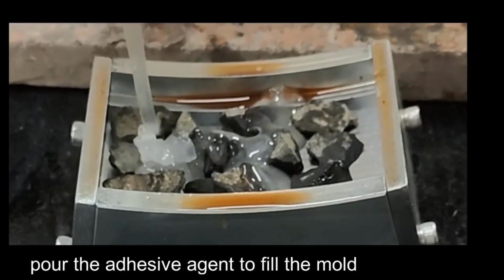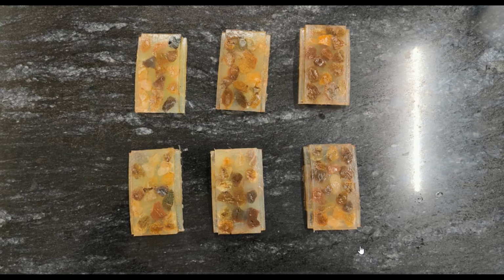to fill the mold. When the bonding material has stiffened sufficiently, strike off the excess material and make the surface even with the curved surface of the mold. And these specimens can be demolded after hardening of the bonding material, and the typical time is 5 hours.